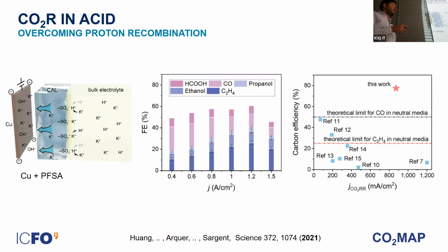But what's more important about this work is not only the Faraday efficiency or the current, it is the carbon efficiency. In all the previous works that I have been showing you, which are these ones at the bottom, the carbon efficiency was very low. That means most of the CO2 that you put in the system, instead of being converted into the product of your choice, in this case ethylene, was transformed into carbonate. So the carbon efficiency was under 10%, and this impacted a lot at the system level, the energy that would be required to regenerate the electrolyte.